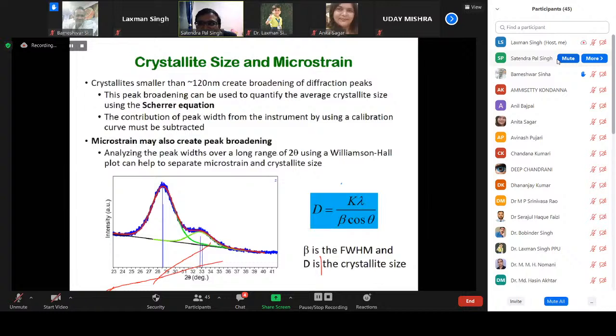The other thing people always use is to measure the crystallite size. Crystallites smaller than 120 nanometers create a broadening of diffraction peaks. This peak broadening can be used to quantify the average crystallite size using the Scherrer equation. Many people working in crystallography use this Scherrer equation, where D is the crystallite size and beta is the full width at half maxima. The full width at half maximum is found by taking the background, measuring the height, and half of this height gives the full width at half maxima at the particular angle. But the most important thing in measuring it is that you have to subtract the instrumental broadening. For that, you have to calibrate your XRD pattern and know the instrumental broadening, which should be subtracted from the given peak.